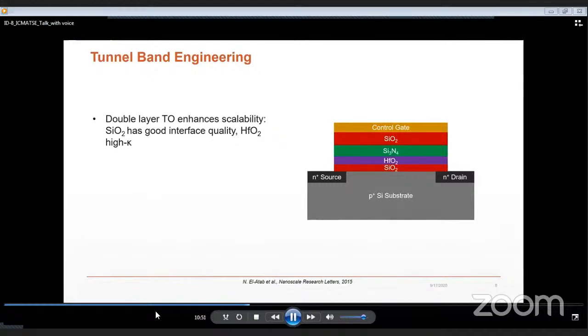In fact, the tunnel oxide of future memory devices would be difficult to scale down if 10 years of data retention is needed. If the tunnel oxide is made fairly thick, extended retention times can be realized, however, at the expense of high program and erase voltages and long program and erase times. Using materials with a high K for the tunnel oxide layer could be one solution. However, higher K usually means a lower or smaller band gap. So an alternative solution is to insert multi-layers of oxides as the tunnel oxide.